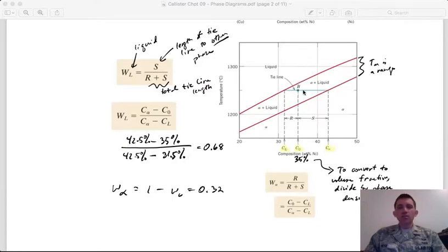So we'll use this diagram here as an example. We're not quite at the boundary. We've cooled down a little bit further. But at this particular temperature, we're forming alpha phase. And to figure out what the composition is of that alpha phase, you draw a line that is parallel to the composition axis. And where it intersects either the solidus or the liquidus, you drop a line down to the composition, and that tells you what the composition is of the liquid and the alpha phase that is solidifying at this temperature, right? So like we see here, they use R and S to define the size of these regions. And so you'd see here the weight percent of liquid, right? So I would draw a line over here and I would have the S region.